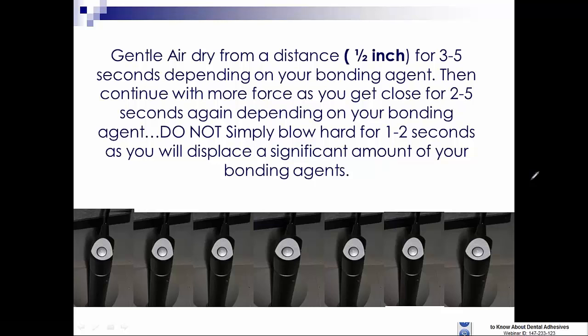less volatile. Then get closer to the adhesive film for an additional 2 to 5 seconds to more vigorously remove the water. If you just vigorously blow for 1 to 2 seconds immediately, you will displace and literally blow off the margins of your preparation, the adhesive that you're hoping to bond the composite to those same interfaces.